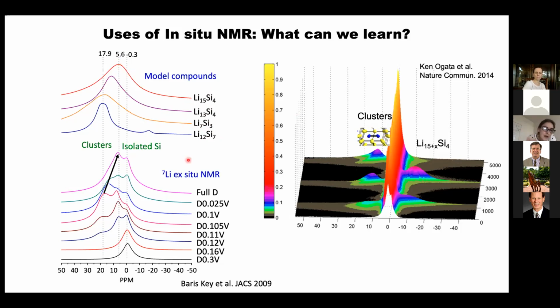And so with that learning, we can then do what we call ex situ studies, where we make lots of different batteries, we pull them apart, and we do NMR. And you can see in this study that when you first lithiate, you form these cluster things, and then when you continue to react, you form the isolated. So this is the ex situ study. And then we moved into the in situ study.